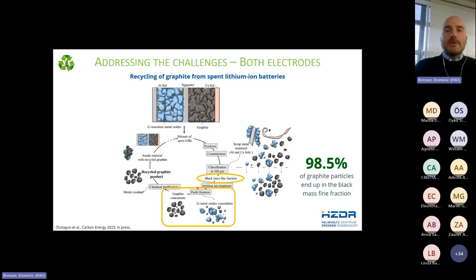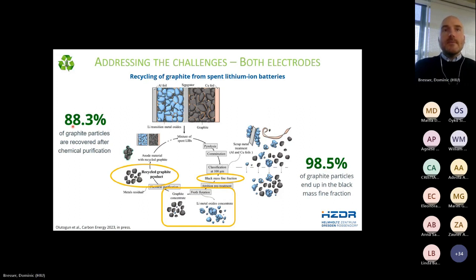Then there's a flotation step where the active materials of the positive electrode and the negative electrode are separated, right? And then there's a chemical purification of the graphite to remove these minor traces of transition metals and transition metal oxides that are depicted here in blue. And then we have the recycled graphite product. And so the recycling rate for this is more than 88%. Which I think is still pretty high, especially if you compare that. Otherwise, you just burn it, right, 100%. So then you end up with 0%. So 88%. Anything higher than 0 is high, right?